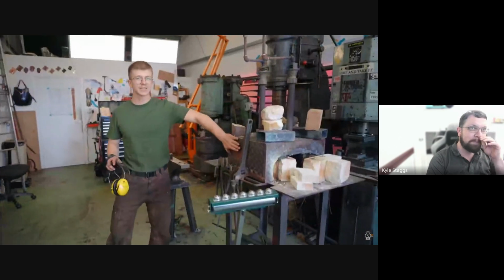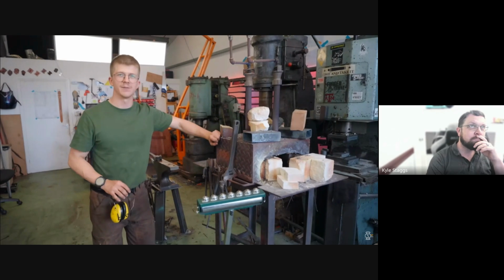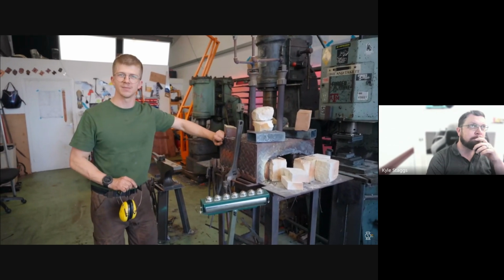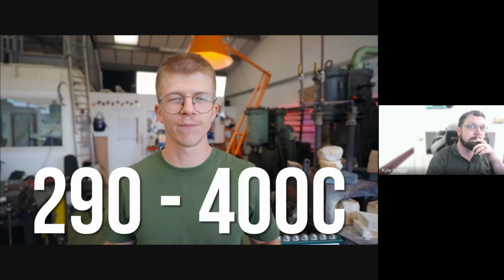It is now time to heat it up and forge it and see if it is any different. So this gas forge gets up to 1300 degrees Celsius, which is about 3 times as much as is required to set magnesium on fire. So of course we don't want to do that. Google says 290 to 400 degrees Celsius is somewhere about the forging range of magnesium, and considering the risk of burning down this entire business park, I think it would be prudent to stick within that range.